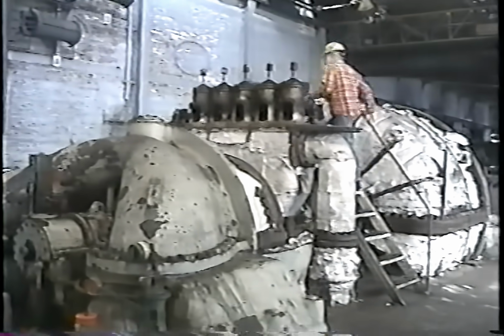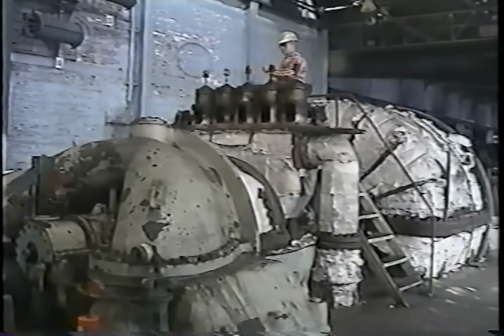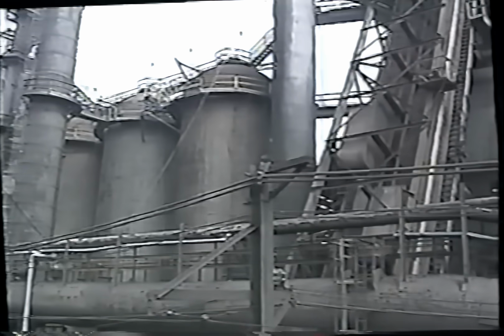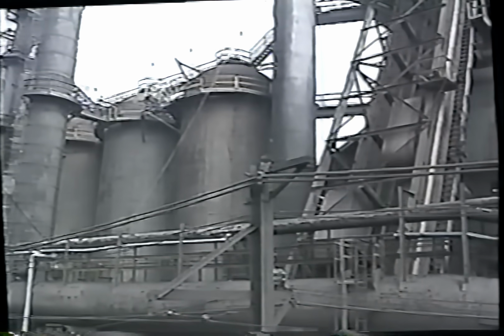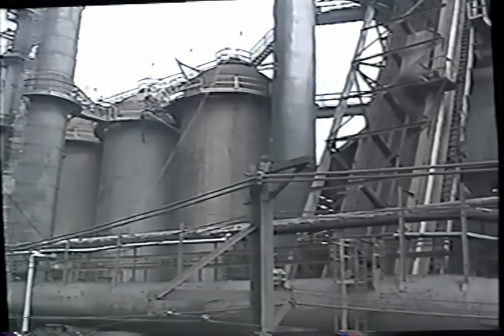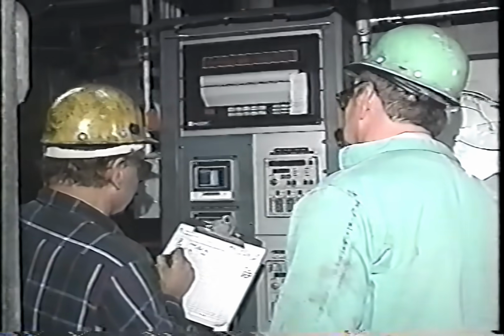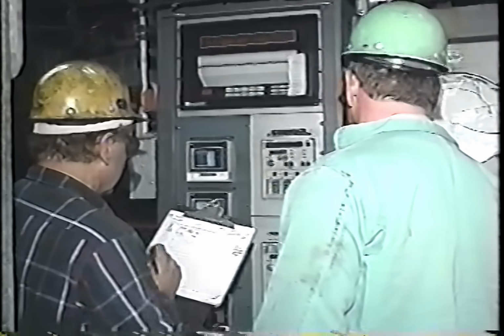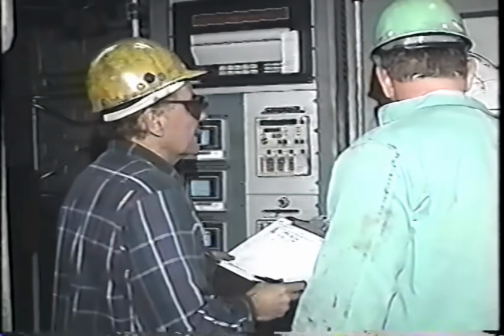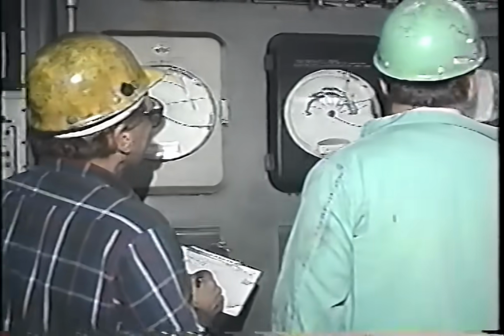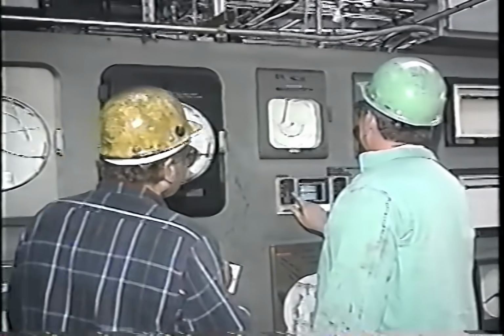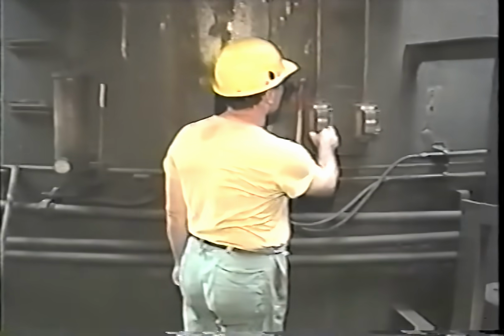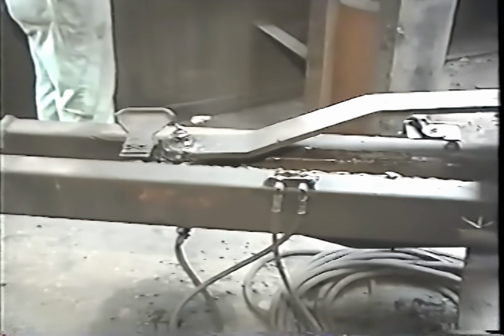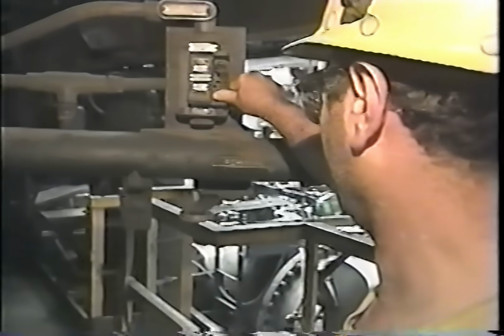The blast of hot air for our blast furnace is generated by the engines and turbo blower in the powerhouse. The cold blast is piped to the stoves, which stand beside the furnace. The stoves burn natural gas and byproduct gas, heating the blast to 1600 to 1700 degrees Fahrenheit. There are 3 stoves at the furnace. Stoves are rotated from gas firing to blast about every 90 minutes.